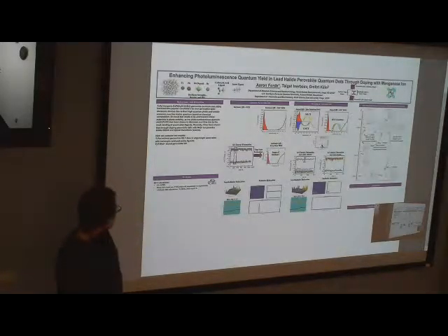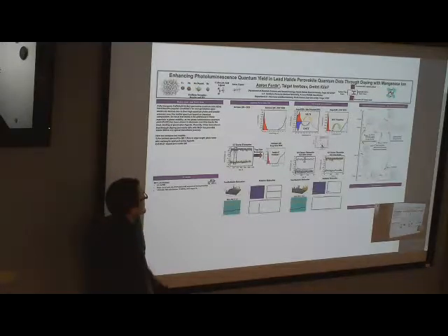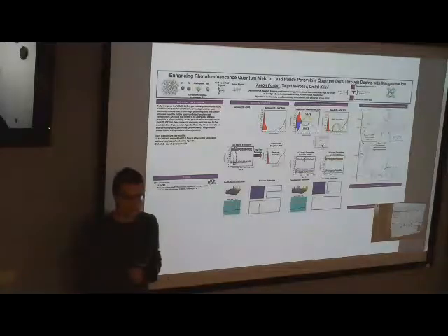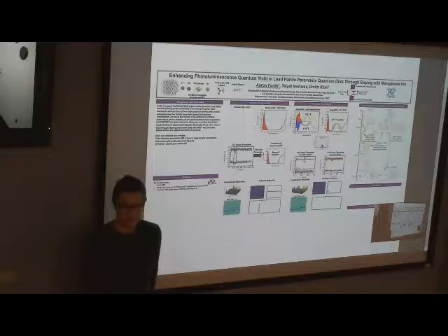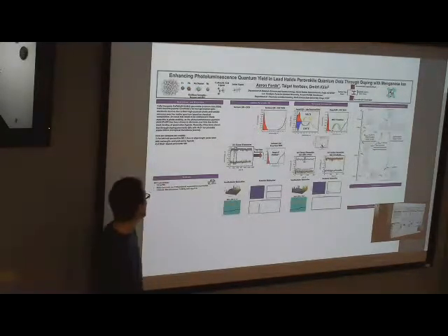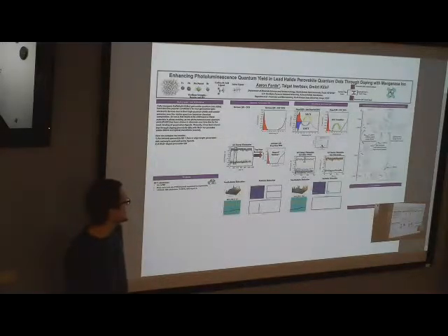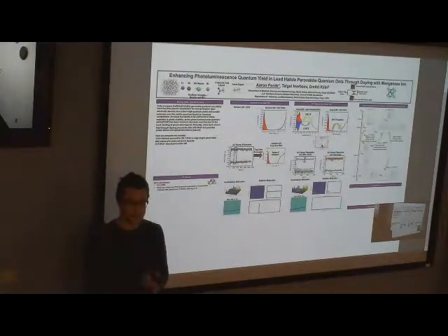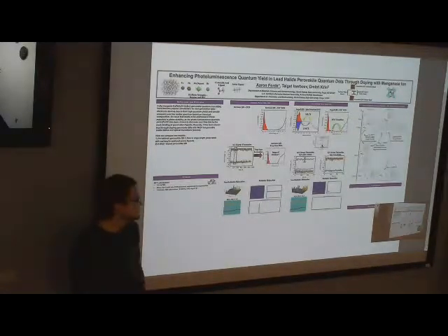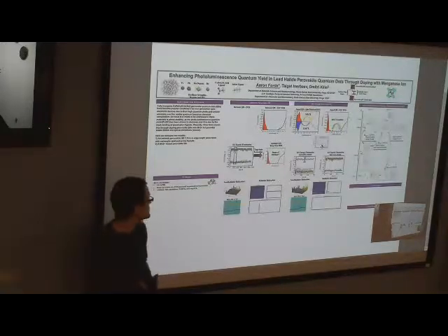And so the methods that we used: for the intrinsic quantum dot, we looked at just regular calculations, and then we also included spin orbit coupling calculations because lead has a heavy spin orbit coupling, just from being a big metal ion. And then for the manganese doped models, we did spin polarized calculations because since we're dealing with a transition metal, it can have various spin states, and we wanted to pick those apart. And then we also included spin orbit calculations with those as well for the ground state.